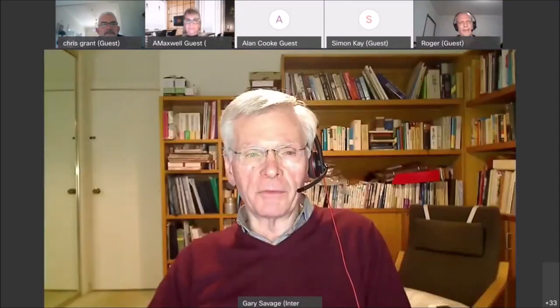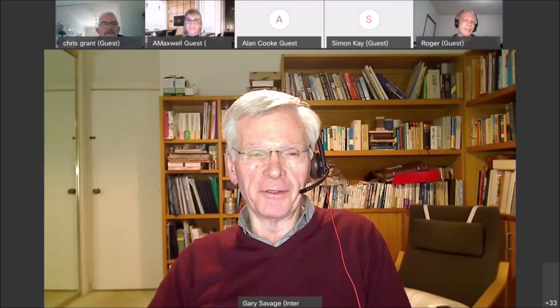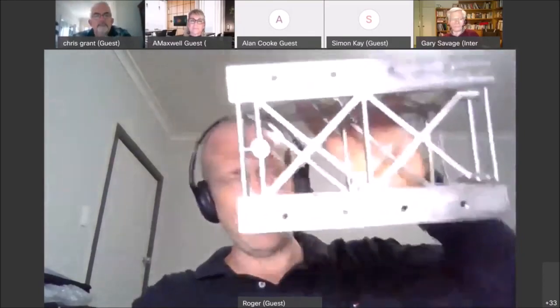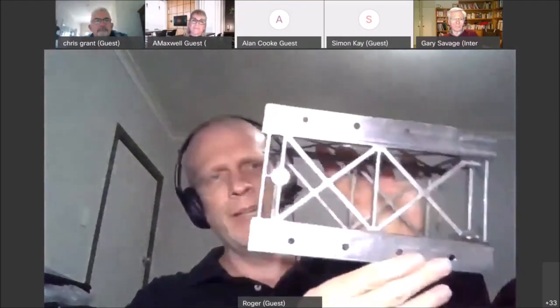So you investment cast it. How do other people manufacture these? They don't machine it out of a billet, please tell me they don't do that. It wouldn't be clever to do it that way, but quite often they are. Currently, they're still struggling with using machined aluminium for a lot of it, and so they're trading off thermal sensor drift for using lightweight materials, which is completely valid, except when your sensors are going to be very sensitive to thermal drift. The way a sensor works is that you can either use a very expensive sensor that calibrates itself, or you can use a dirt cheap sensor in a frame that doesn't move around. So there's a big advantage in having this low coefficient of thermal expansion. A part like this is about 2 kilos by the feel of it. I just can't remember the weight on it, I haven't written it on it, but it's only about 2 kilos or so.